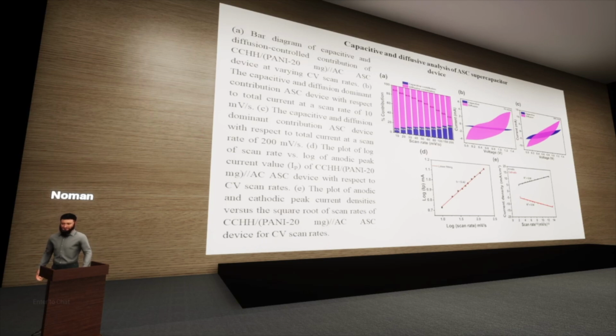This is also the log of the peak current density versus log of scan rate, and this is the current density versus scan rate graph. And these values show that the R square value was very close to one, which means that the diffusion control mechanism was more involved in the device.